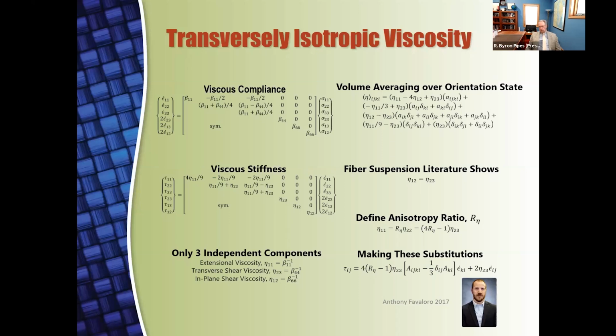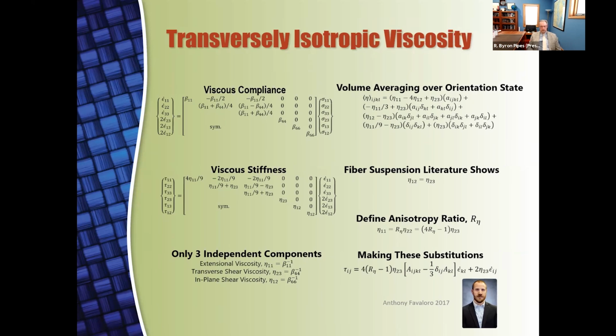In our work, we've proven that the eta 1,2 and 2,3 were equivalent, so you can see the reduced constitutive relationship in the lower right, in which we have the fourth order orientation tensor, and really only one viscosity term remains.